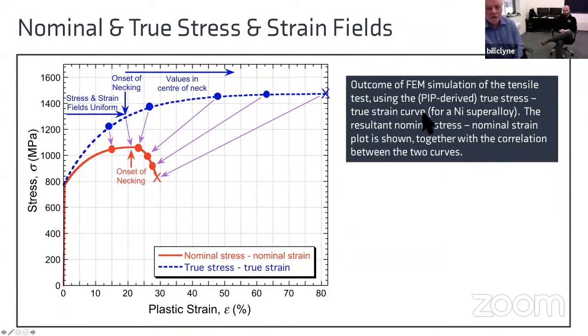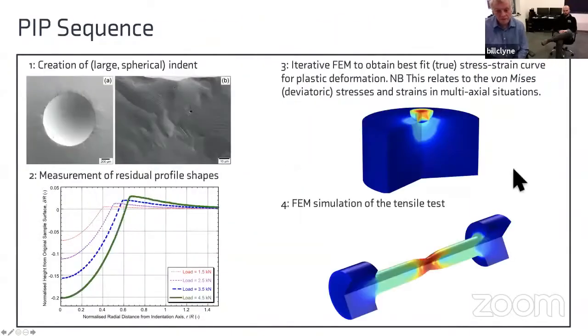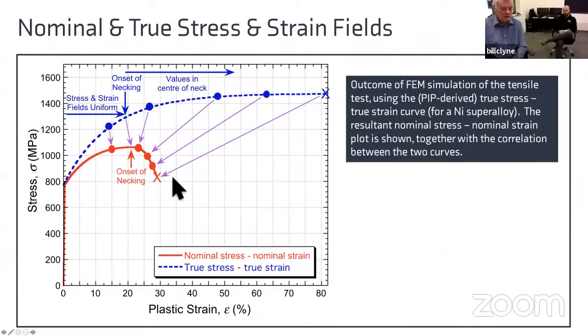So this is the outcome of FE simulation of a tensile test, a particular one. This is the true stress, true strain relationship for plastic deformation. And you can simulate when necking will start. In this particular case, it's here at about 20% strain. Up to that point, the stress and strain fields are uniform. Beyond that, obviously you get a lot of inhomogeneity as the neck starts to develop. And the true strain in the neck is being monitored here, and then it's fracturing at a certain point, which is actually often something you can predict in terms of a critical value of the true strain in the neck being reached, in this case about 80%. So that's the kind of thing you can do.